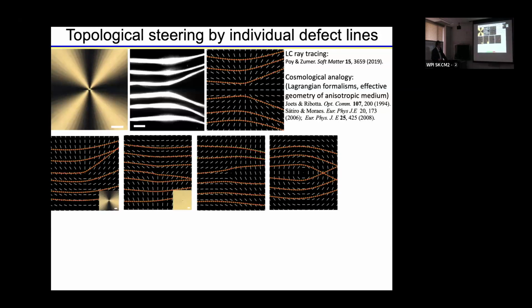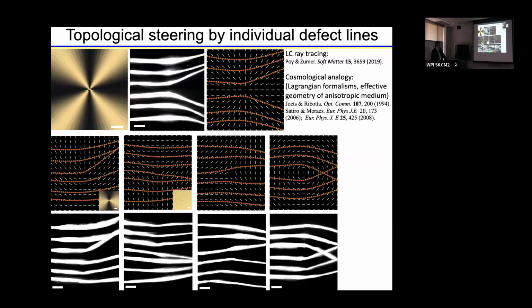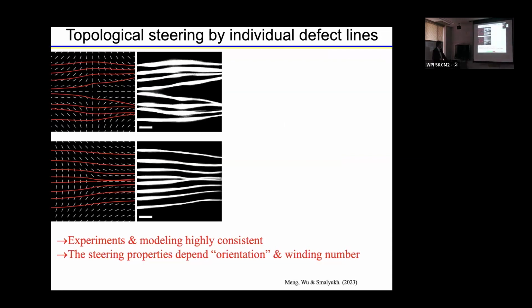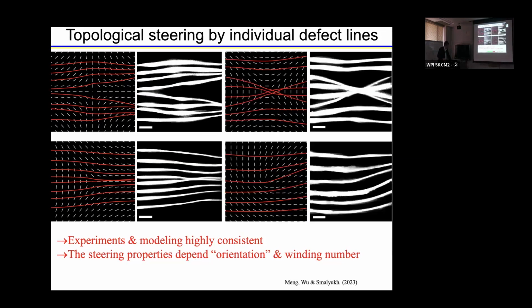And so now we can pattern different types of vortices. For example, in here, you can see half integer one with this kind of different structure, and you can see how it would deflect light when beams are coming from this side, or the -1/2, this one is +1/2, with different orientations of incoming beams. And in this case, with concentric orientations of director. For all of these, there is a very good agreement with experiments, right? So the modeling of two different kinds very closely captures the experimental behavior. But now I give more examples. So in here is a -1. So these are objects, as you recall, in 2D, right? So you have -1 and -1/2. And again, there is a very close agreement of their behavior for the other different orientations as well.